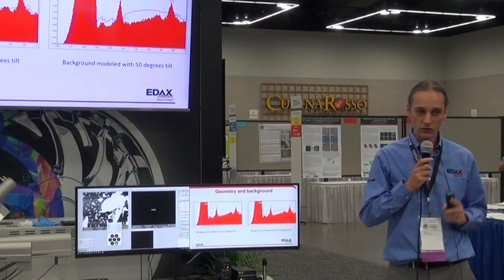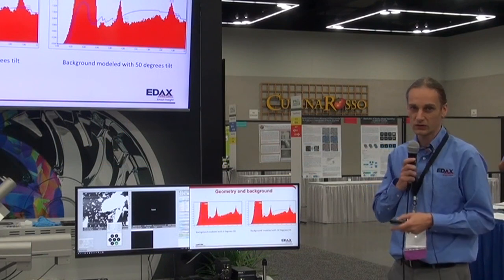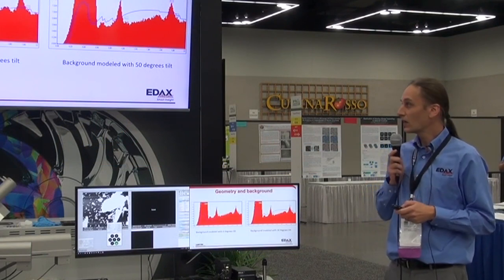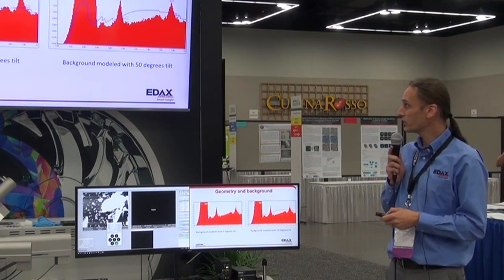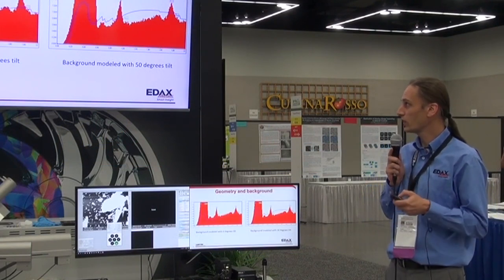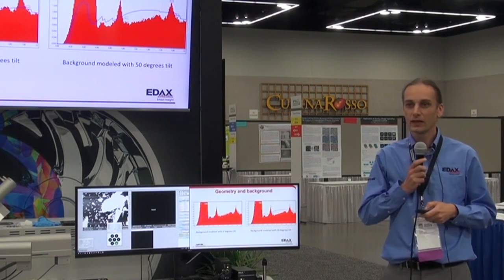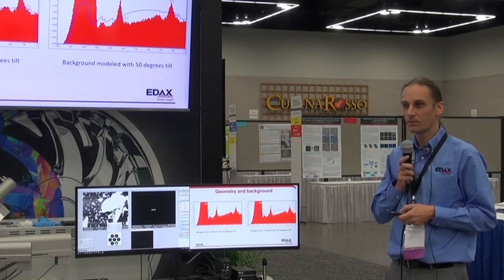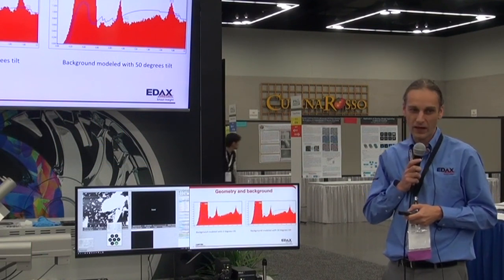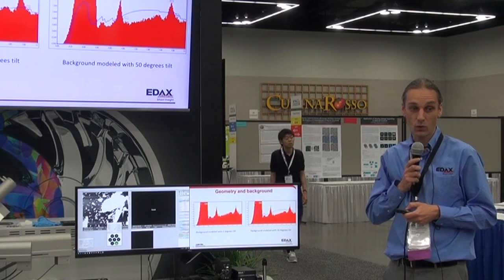So for something like a fracture surface, the SNP model may be good — it'll give you a pretty picture and make qualitative analysis easier. But if you see a large misfit between your sample and the Bremsstrahlung model, that's a big red flag to not click the quantification button.